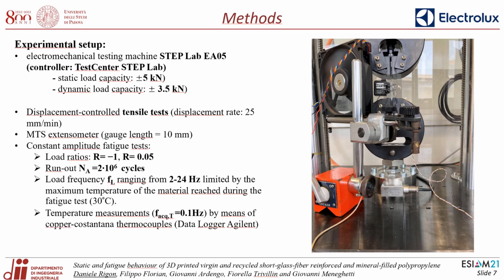Recording the strain, the engineering strain, we use an MTS extensometer with a gauge length equal to 10 millimeters, and the constant amplitude fatigue tests were carried out with two load ratios, -1 and 0.05. The load frequencies applied ranged from 2 to 24 Hz, and it was limited by the maximum temperature of the material reached during the fatigue test.